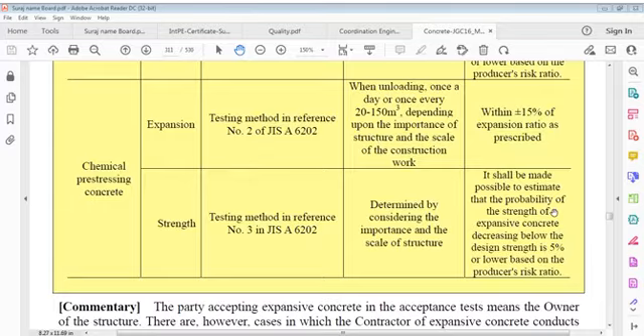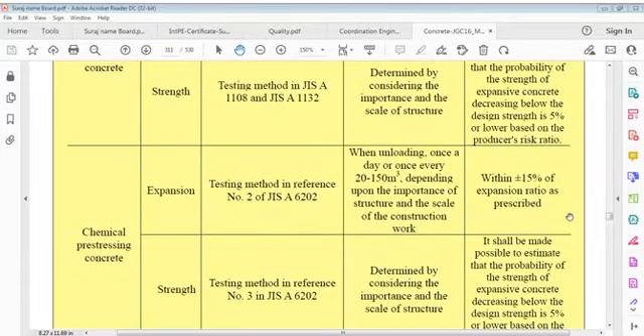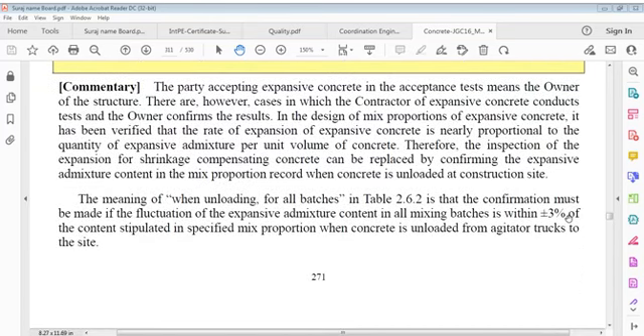Strength is determined by considering importance and scale of structures. It shall be possible to estimate that the probability of strength of expansive concrete decreasing below design strength is 5% or lower based on producer's risk ratio. Result commentary: the party accepting expansive concrete in acceptance tests means owner. There are, however, cases in which contractors of expansive concrete conduct tests and the owner confirms.